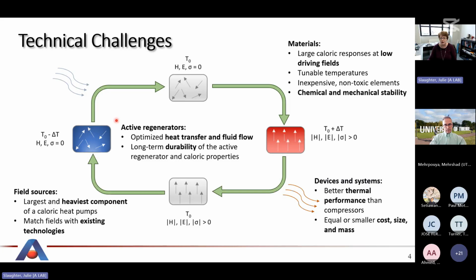So now you're cooler than you started. And then you absorb heat from a load, an external load, another heat exchanger there. So you go through that cycle, and you can build up a temperature span larger than the material itself. So if the material itself changes, this delta T is 5 degrees Kelvin, you can actually generate a temperature span 3 to 4 times that quite easily.